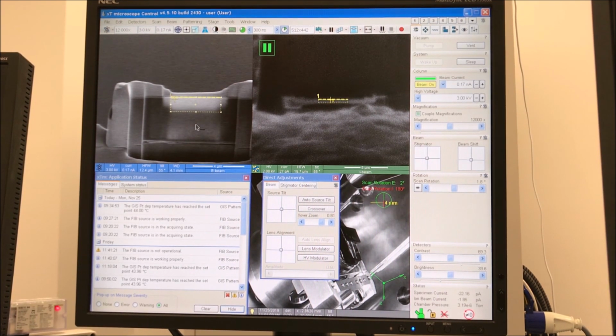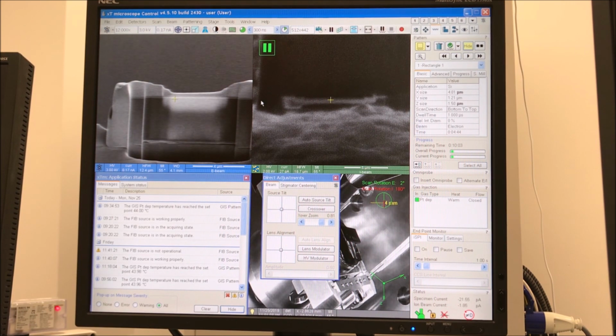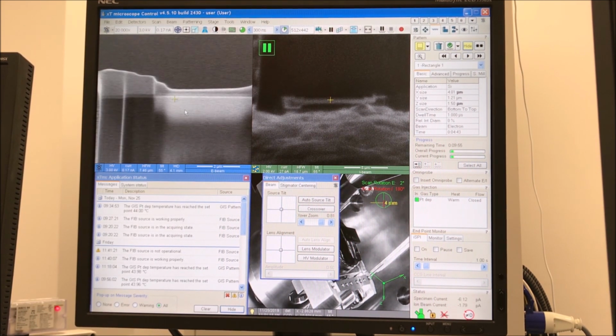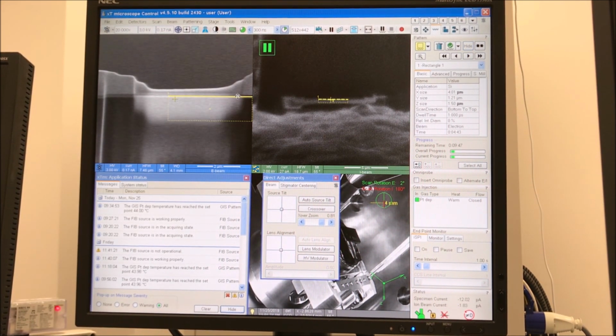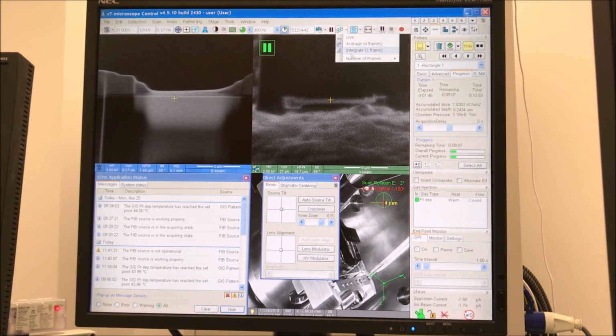So one trick that I use is to draw a rectangle pattern in the E-beam image and then use a scan rotation of the E-beam to align the surface perfectly left to right, and then I can position that pattern right at the wafer surface and use that as a clear indicator that I still have my surface present.